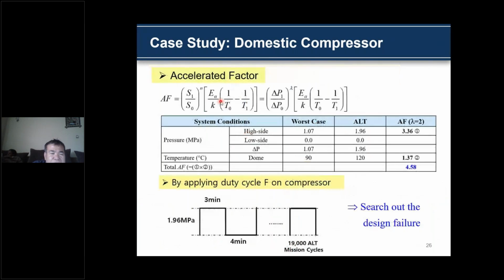I will explain how to derive the acceleration factor. As I mentioned before, the acceleration factor depends on the ratio of the pressure difference and the temperature difference. For the worst case, the pressure difference is 1.1. For accelerated life testing, we increase the pressure difference to almost 2. The acceleration factor is 3.4.